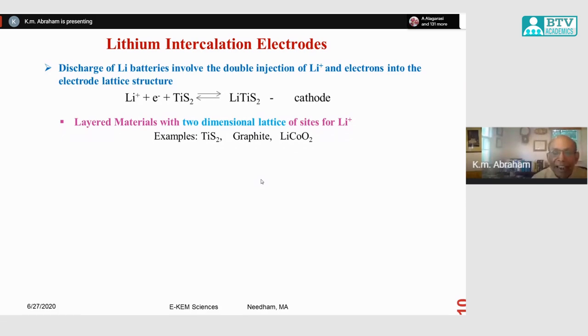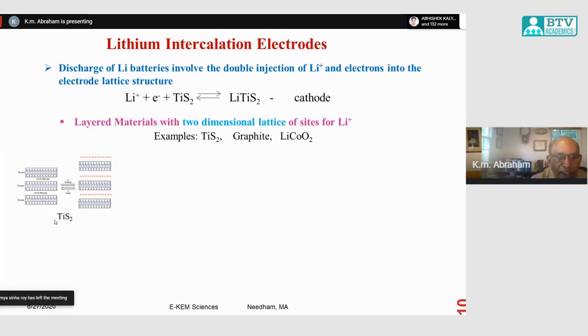Titanium disulfide is a layered material with a two-dimensional lattice of sites. So you have here a schematic representation of the titanium disulfide lattice. So you have these TiS2 units stacked one on top of each other like this, and with an interlattice spacing between these titanium disulfide layers in the crystal. And the interlattice bonding there is very weak. They are a van der Waals type weak bonding.